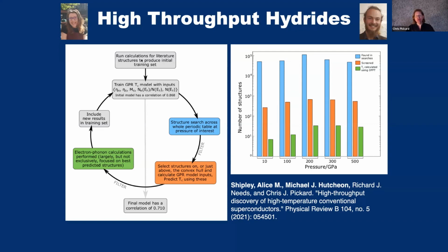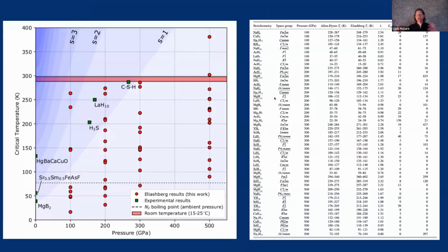And then on top of that, we built a simple Gaussian process-based machine learning model to look at a few of the electronic structure parameters to guess whether the structure was likely to have a high TC, which allowed us to only have to do of order 20 or so TC calculations each time. So we filtered down from 100,000 to about 20 and then did the DFT calculation of superconducting transition temperatures. And then we ended up with this result here.